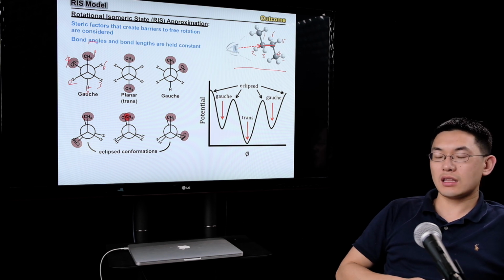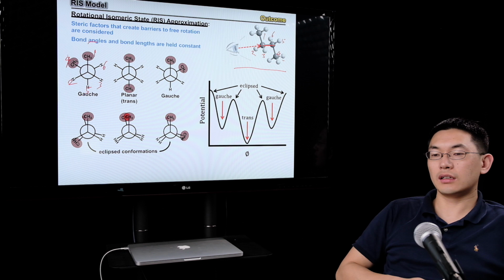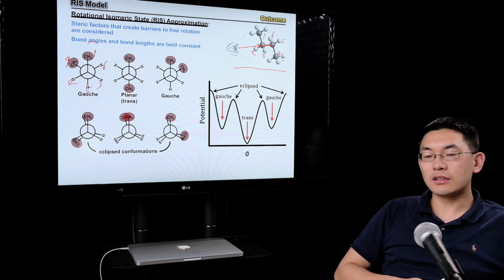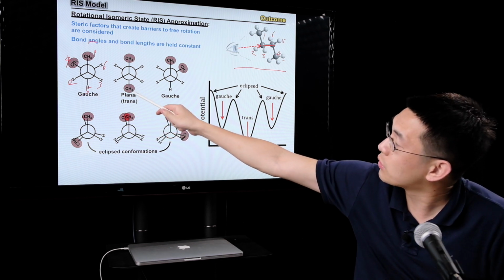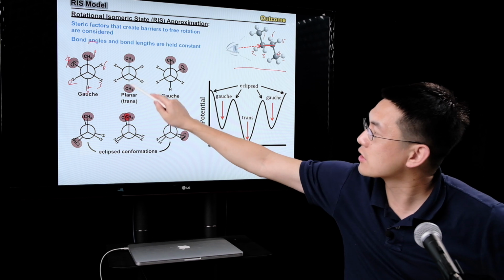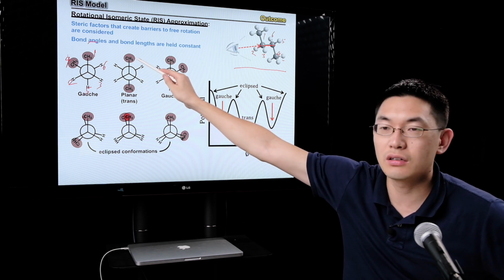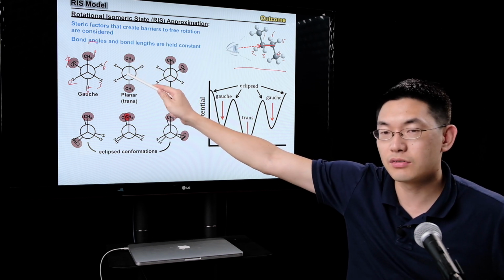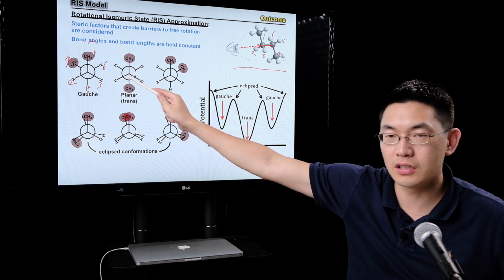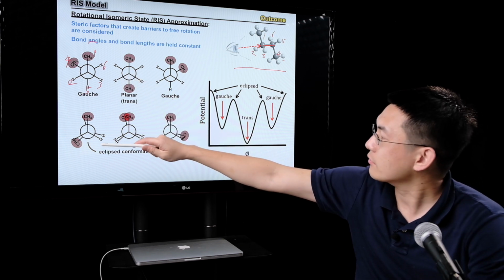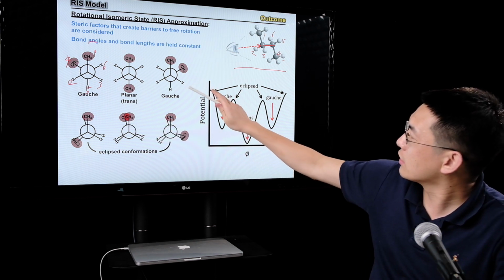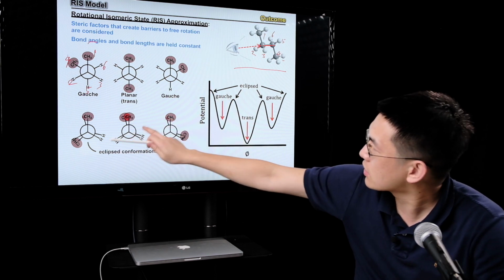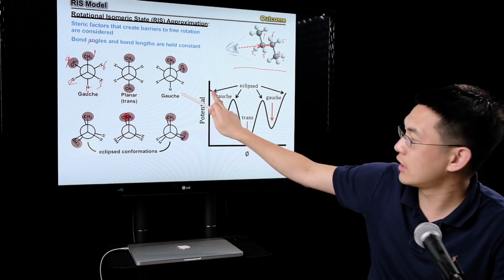And you can understand that because your chain is sitting not overlapping on the other state, but also in a local energy minima, right? And this trans will result in minimal bulkiness because these two are large chain groups. And when they are getting close, they create a lot of steric hindrance, like shown here, where you can see this would be representing these states. They would represent both high energy states.